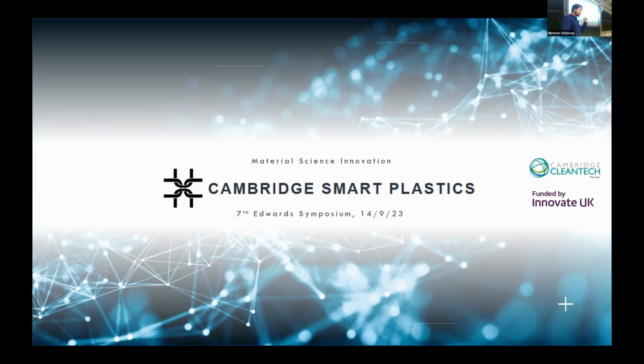We did do a project with covalent bonding, inspired by a paper by Wolf, where we did some covalent cross-linking. And I do know, to your stiffness point, that where it's the entire plane bonded, it's only one plane which breaks. We made a very good welding thing with vitrimers. Actually, you can weld vitrimer plastics because they bond exchange, and it becomes, to me, a three-dimensional bond. And every time we functionalized a surface and bonded it, it was incredibly brittle because you only have one plane, and so the crack propagation is very easy. So that would be my 5 cents on the direction you're working in.